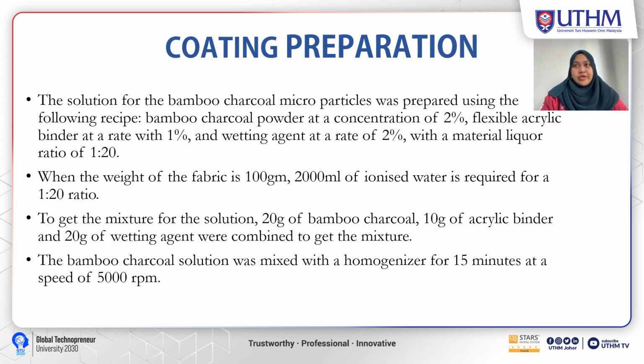Next, it will be the coating preparation. The solution for the bamboo charcoal microparticles was prepared using the following recipe: bamboo charcoal powder at a concentration of 2%, flexible acrylic binder at a rate of 1%, and wetting agent at a rate of 2% with a material liquor ratio of 1:20. When the weight of the fabric is 100 gm, 2000 ml of ionized water is required for a 1:20 ratio. To get the mixture for the solution, 20 gram of bamboo charcoal, 10 gram of acrylic binder and 20 gram of wetting agent were combined. The bamboo charcoal solution was mixed with a homogenizer for 15 minutes at a speed of 5000 RPM.